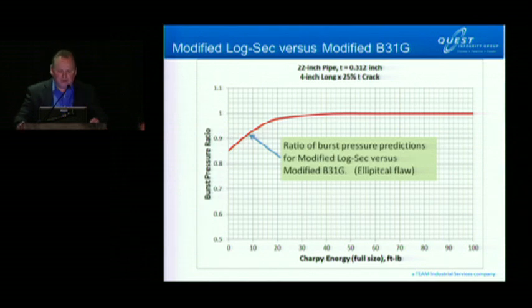This is a plot of burst pressure versus Charpy energy, normalized by the B31G equation. Above about 30 foot-pound Charpy energy for this particular pipe configuration, you get essentially the same answer in burst pressure as you do from B31G. As you reduce toughness down to 0, the predicted burst pressure is still about 85% of what the metal loss equation gives you. So this adjustment factor removed the dependence on toughness. So you have an equation that's almost insensitive to toughness in predicting burst pressure.